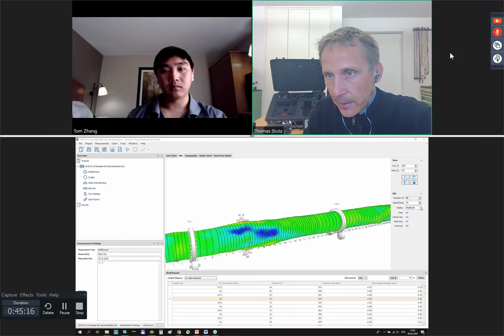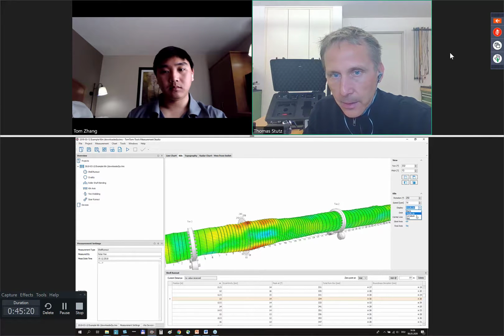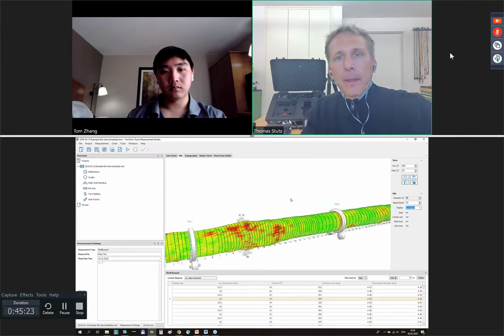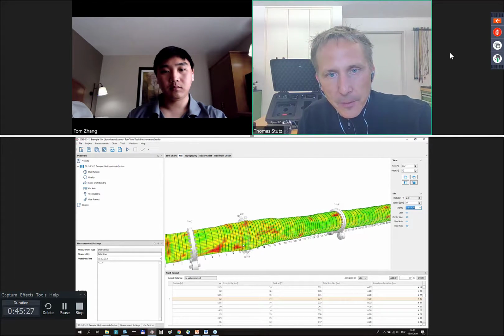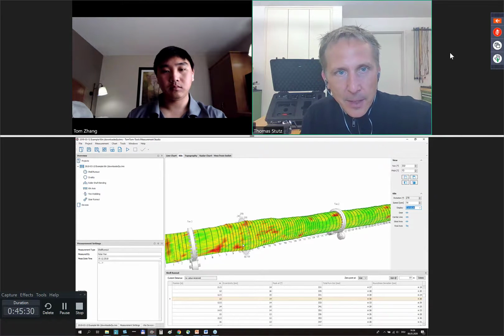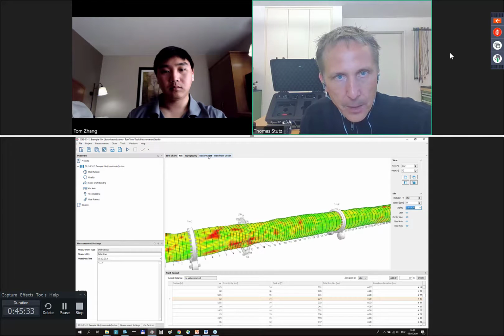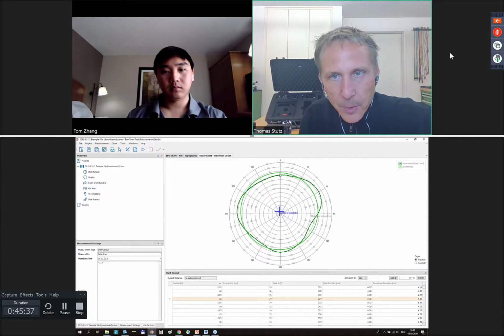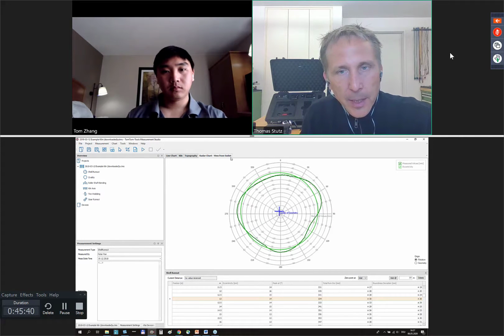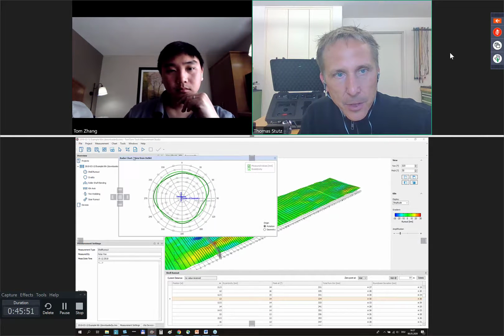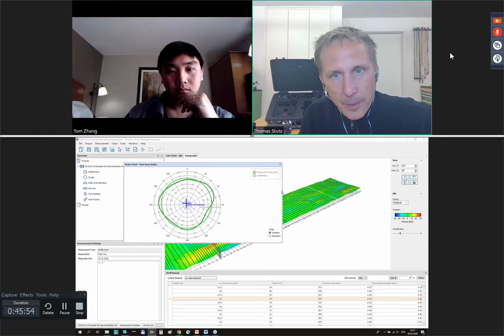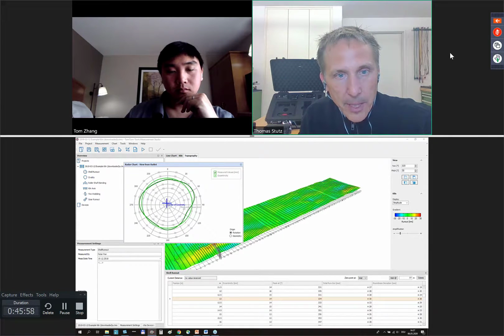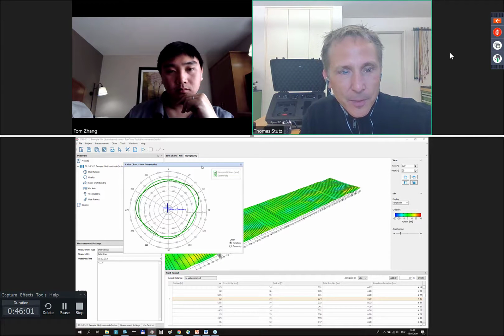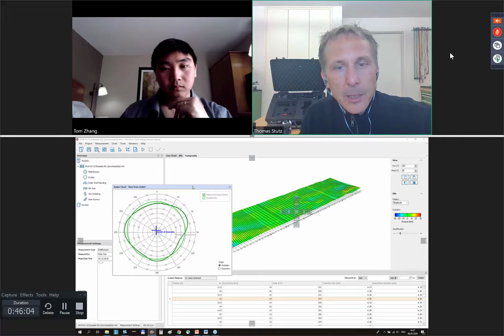And for that we have added the curvature view, and this is here. When we go for curvature, you see what is here is heavily deformed, but still it's not that bad, because in the radar chart you see that these are somehow smooth curves. It's not nuts, but it's also not that bad, even with high values. We are talking about plus minus 30 millimeter, but these deviations are not that sharp, and that's why it's not so critical. If somebody would ask, would you recommend to replace this area of the kiln shell, I would say, yeah, first have a look into the brick life.